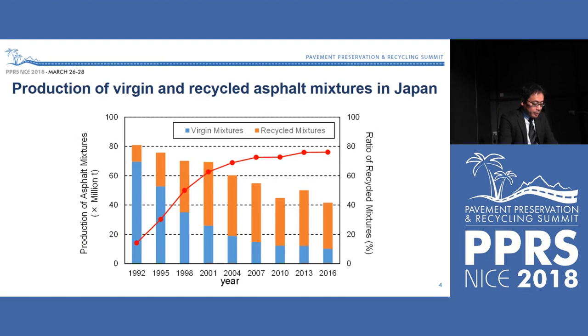What you see here is production of virgin and recycled asphalt mixture in recent years in Japan. You can see the ratio of recycled mixtures to the total proportion of asphalt mixtures has been increasing. The ratio was only 14% in 1992, but it exceeded 50% in 1998, and it reached 76% in 2016. The recycled asphalt mixture has already been used as a general mixture in Japan.